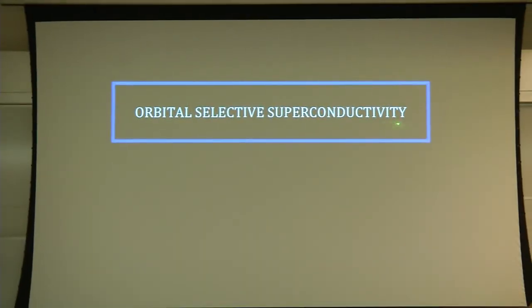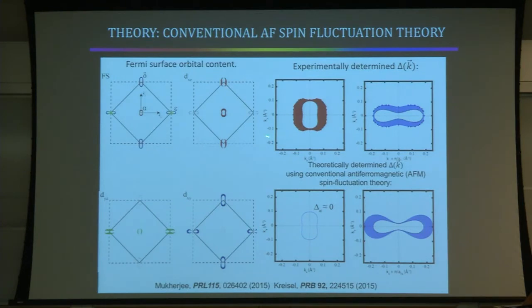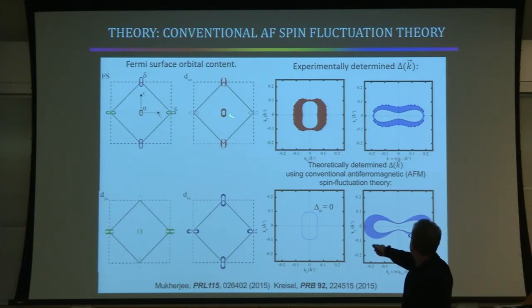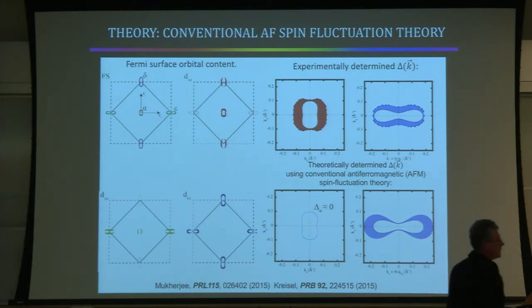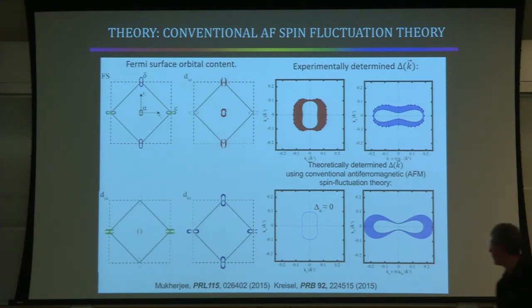So what we're after is orbital selective superconductivity. The first thing you can say is, let's take this Fermi surface, and here's the measured gap structure. Now let's go to the literature, specifically this literature, and look at the predicted gap structure for antiferromagnetic spin fluctuations where all the quasi-particles are coherent, which is here. There should be virtually no gap on this low Q band, and there should be a large gap on this band, but it should be orthogonal to the direction in which we detect the large gap. So there's essentially no correspondence between the spin fluctuation theory for the gap structure and what's observed.